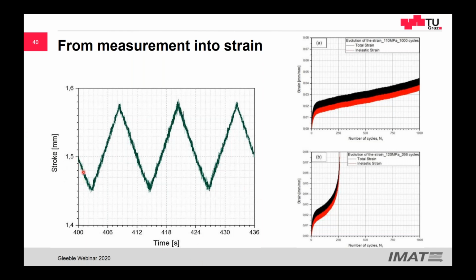Good, and then we got a signal like this, the stroke. Okay, it looks very strange. And we also got the L gauge, which looks nicer. And with this signal, the L gauge, we extract two things. The total signal is the total strain, this black here. But we were interested only in the inelastic strain, which means we had to extract the thermal expansion out of it. This sounds trivial at the beginning, but it was not. And after we did this, we got the inelastic strain.